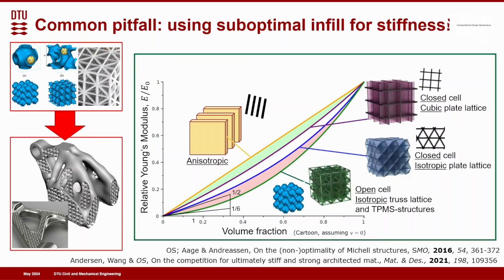So I think this is very important. If you are lightweighting, you are not doing that with suboptimal microstructures. It gets better if you use the isotropic closed-wall cell structure, that's the blue one, but the very best is the rectangular structure where it's oriented optimally along the stress directions. So I think this is very important to realize when you are talking about lightweighting.